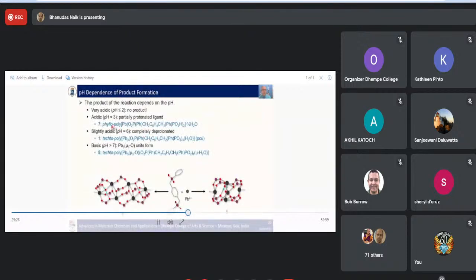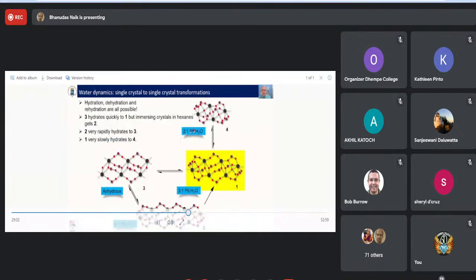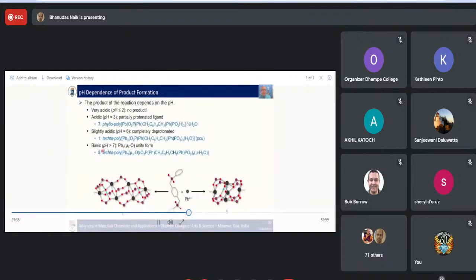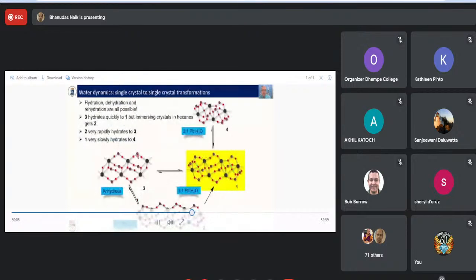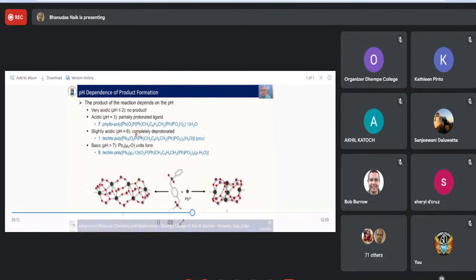We also found 7 compounds. We have 8, which forms if you have a really basic solution, where you begin forming compounds with an oxo ligand. If you have a very acidic solution, you have no product. If you have a fairly acidic solution, as you saw before, you have a monoprotonated ligand, so you form 7, which is a monoprotonated compound. This is a PCU structure. Basically you have this oxo ligand here, and 1 is this compound here. So you have a difference in the compound depending on whether you have an acidic, slightly acidic, or basic solution.